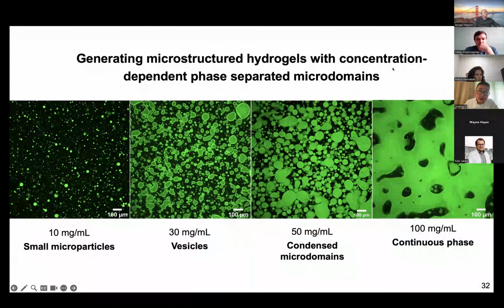We can also change that with your concentrations. At 10 mg per ml, you have the small particles. At 30 mg per ml, again, you have these vesicles, and then at 50 mg per ml, which is a high concentration, you have these multi-domains, but mostly condensed microdomains as well. At the high concentration, you have continuous phases as well.